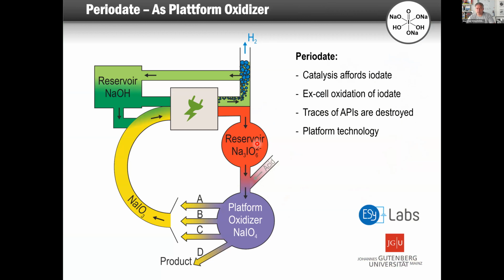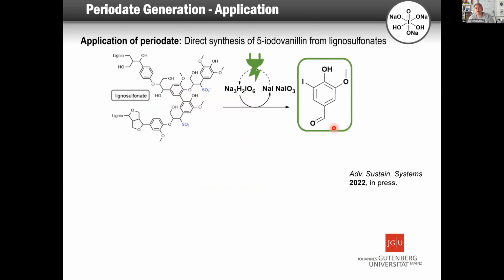There's another ex-cell version I want to introduce to you. That's the periodate, and the periodate can also be made electrochemically in a similar way. Here we need a divided cell. It's a kind of platform chemical, and you will see you can use the periodate to make different reactions by catalysis and even for API synthesis, but we are looking for our own lignin. And you can convert here, lignosulfonate was used. We just used that directly with the electrochemically produced alkaline periodate.